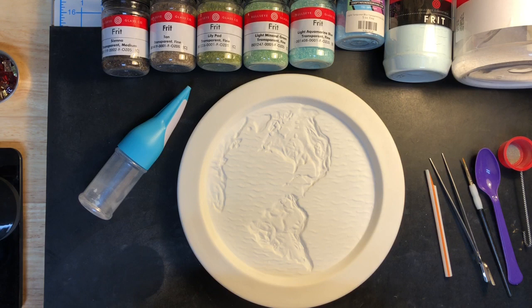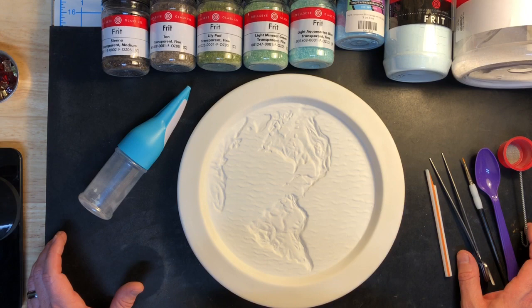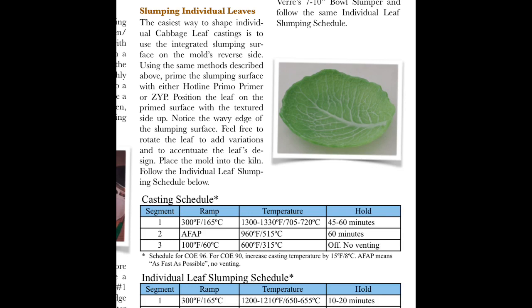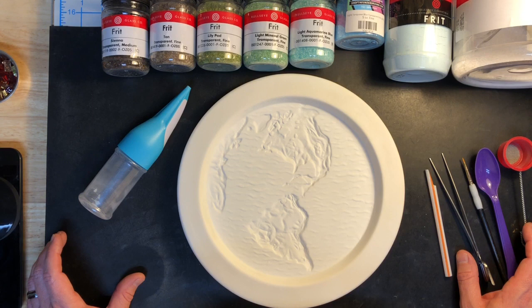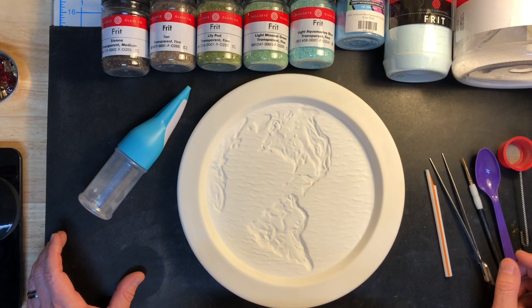There is no schedule or instructions from the manufacturer. What I found is there's a Colour de Verre mold — a cabbage leaf mold — that looks a lot like this in terms of size and fill weight. I remember the first time I did this I roughly followed their firing schedule and it worked pretty well, so that's what I'm going to do here. I need to hit about 350 grams of glass in here to get the results I got the first time.